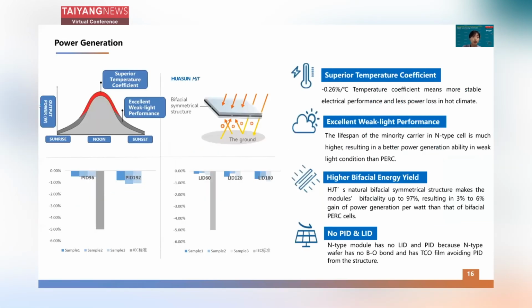And this is about the high efficiency advantages. The HJT cell structure itself has inherent higher power generation advantages. Let's say it will contribute to these 4 points, including the superior temperature coefficient, low to 0.26. Because of this low temperature coefficient, the module could have less power loss in very hot climates. And based on the N-type wafer, the excellent weak light performance will be achieved so that the module can have better power generation ability in weak light conditions.